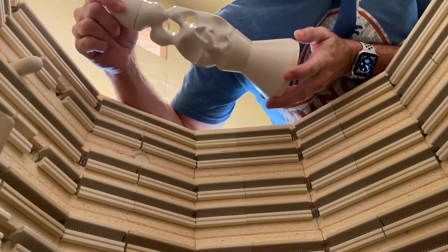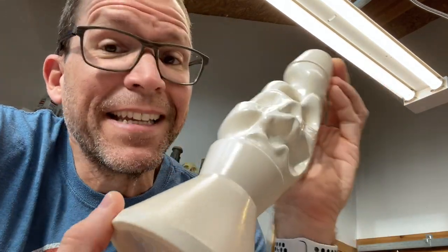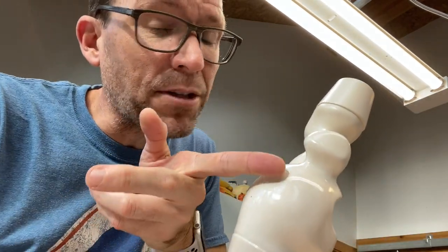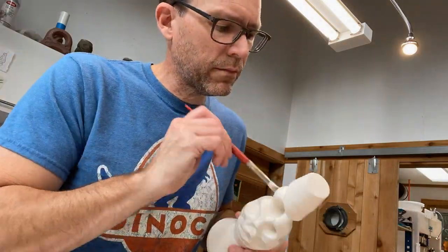Nice and shiny. Fortunately, this will look fantastic covered in gold luster. I'm examining closely the gloss white spray application. It's okay, but there are areas underneath here where there's still rough clay visible. My concern is that will show up — you're going to see high gloss when the gold is applied, but it's going to go dull underneath the cheekbones. I think I'm going to risk a second application of white gloss and a second glaze firing. Considering that we're actually committing real gold to this thing, and I've already spent hours in that spray booth sanding it down, I think it's worth doing a second glaze firing just to get things perfect.